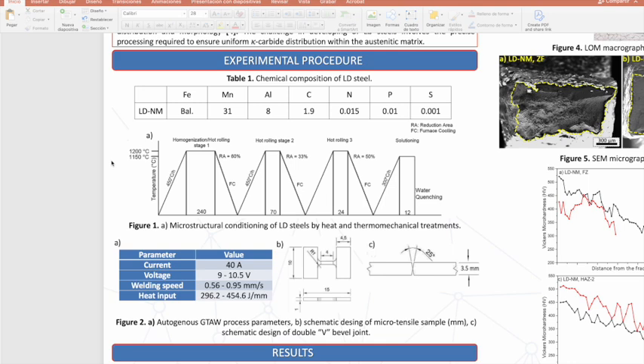Experimental procedure. In Table 1, the chemical composition of the LD steel used is shown. Iron balance, manganese 31%, aluminum 8%, carbon 1.9%, nitrogen 0.015%, phosphorus 0.01%, and sulfur 0.001%. In Figure 1, a microstructural conditioning of LD steels by heat and thermomechanical treatment is shown. In Figure 2, A. autogenous GTAW process parameters, B. schematic design of micro-tensile sample in millimeters, and C. schematic design of double V bevel joint are shown.